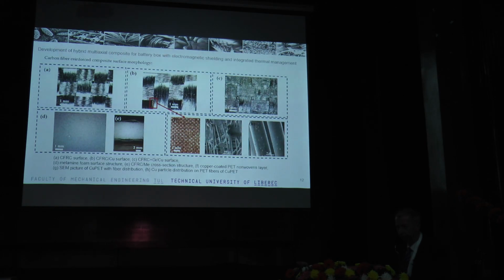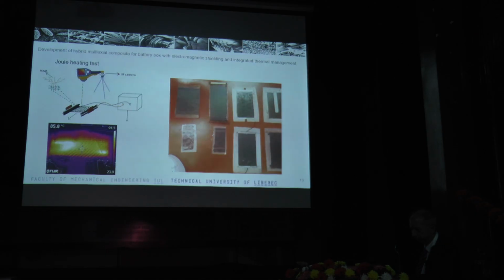In this picture you can see some micro pictures from microscopy—there is the carbon surface, this is a layer of carbon, and under that you can see the copper. Here is one with graphite particles, melamine foam, and this is microscopy of the copper non-woven fibers. It's a commercial product we buy.